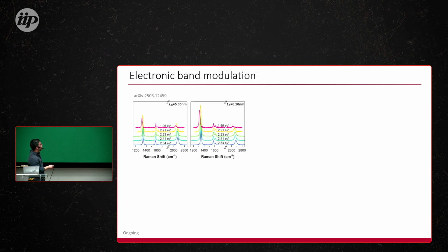This is for a considerably low concentration, and this would be a higher concentration of borons, just to demonstrate that we have the same behavior. Only the intensities, of course, are changing. And also notice that the downshift that we have for the red laser over here, which is 633 nanometers, is more shifted than the other ones. And I'll explain a little bit why.